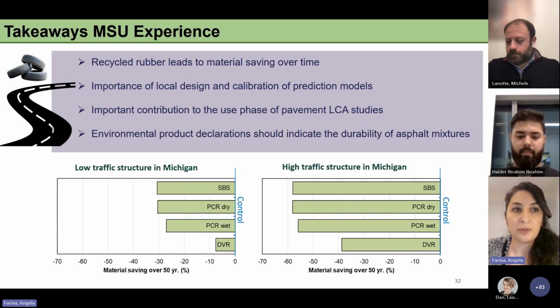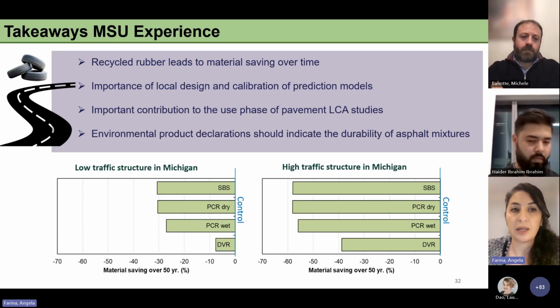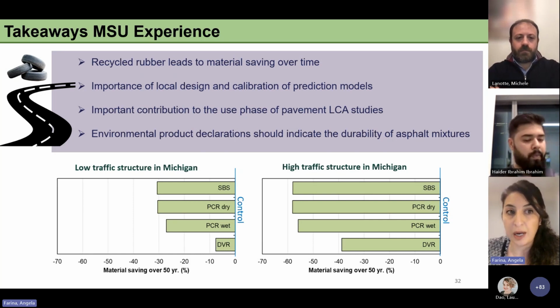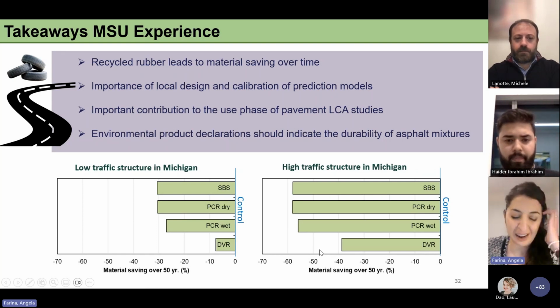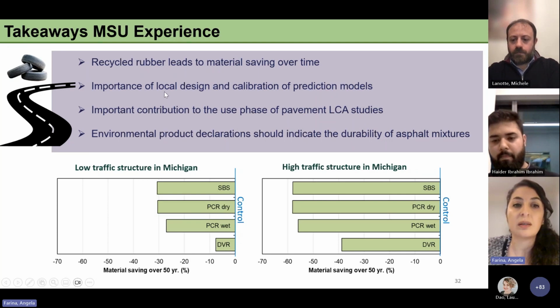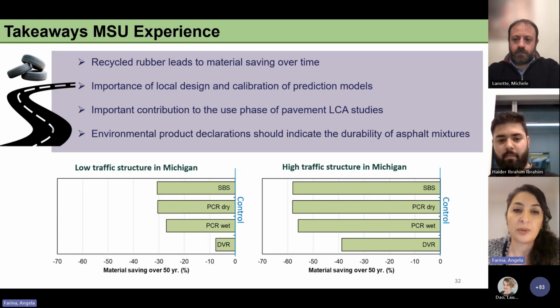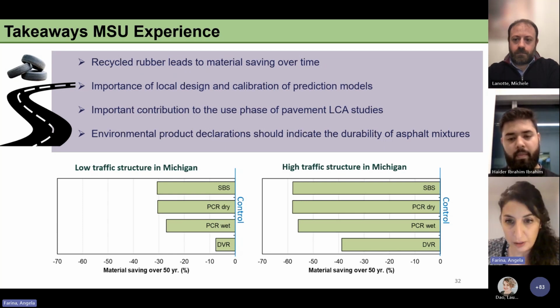So to sum up this part of the work, we can say that the recycled rubber leads to a material saving over time, because I calculated that we can save up to 58% of the material using the PCR dry and or the SBS in Michigan for a high traffic structure compared to the control mix. And this also leads to the importance of having a local design, local calibration for the prediction model, and the importance of including the use phase in the pavement LCA studies, as well as in the EPDs that should indicate the durability of the asphalt mixtures.